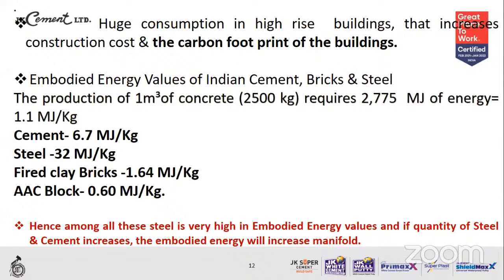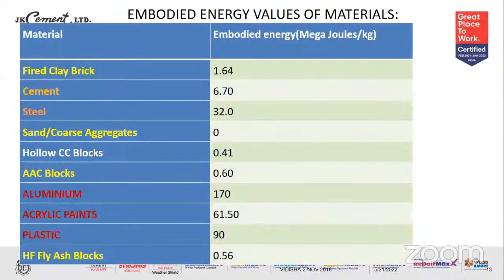So it's a very conscious decision that we can take, replace fired clay bricks with AAC blocks. Similarly, instead of going for OPC, let us switch to either PPC or slag cement or the triple blend cement in the concrete, so that we can minimize the carbon footprint on account of EBE calculations. So hence, among all these, steel is very high in embodied energy values, and if the quantity of steel and cement increases, the EBE content goes manifold.